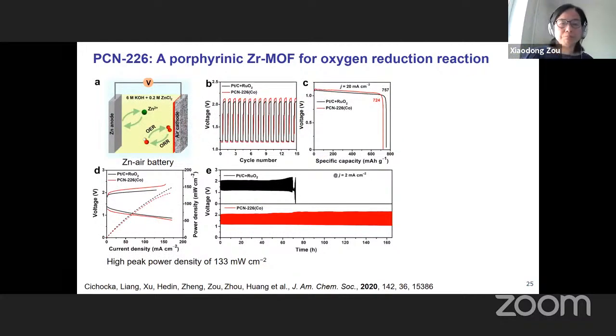This can be used for example to make a zinc-air battery, as you see here. You have the zinc as anode and the MOF as cathode. It has very good recycling, and it has a very high peak power density, 133 milliwatts per square centimeter. And it is much better than the platinum one. I mean, this is just a transition metal, so we can get rid of the platinum in this case.